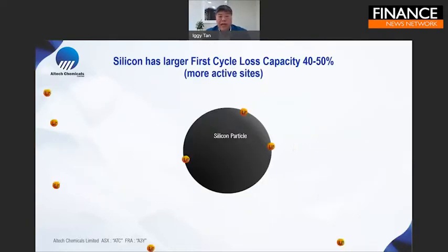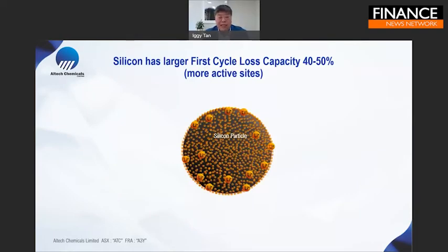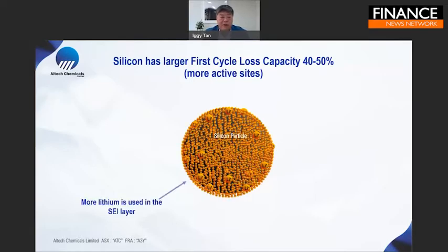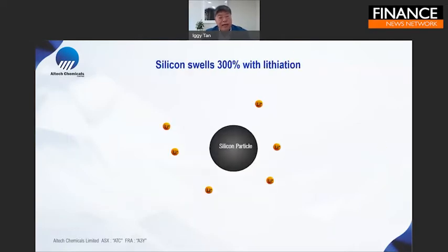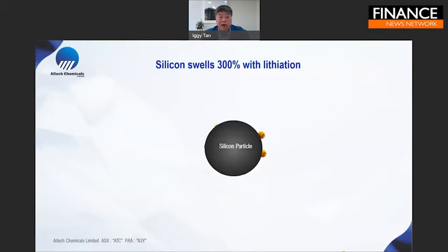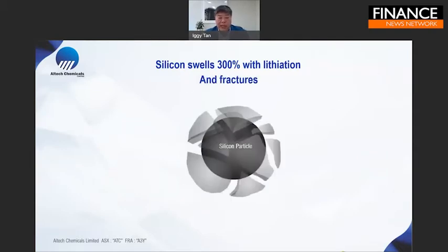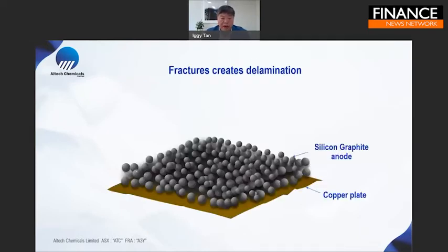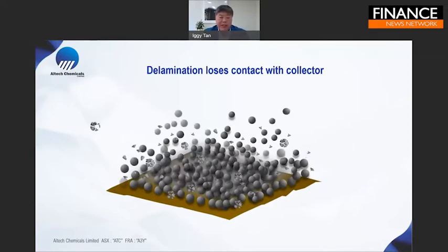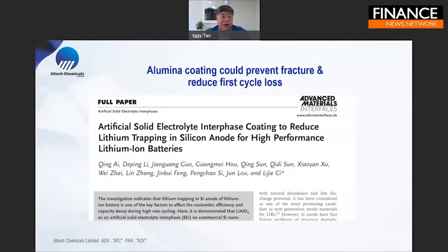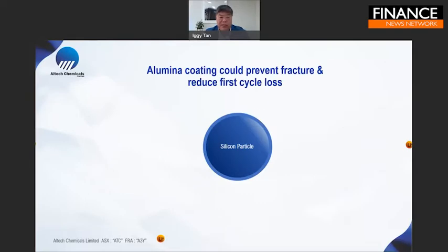I mentioned that the first cycle loss capacity is much higher. It absorbs more lithium in the SEI layer and makes it inactive. So this is the other big problem. And I also mentioned the lithiation, where the volume change is 300%, to the point it actually fractures. Now, when the silicon particle fractures in the anode material, you get delamination, and that's a problem for the battery. So these are the major three problems with silicon material. And there is research that's been done where they've used alumina coating to prevent the fracture of the silicon material. So that's what we're doing.